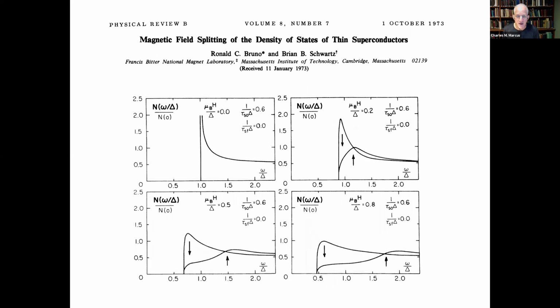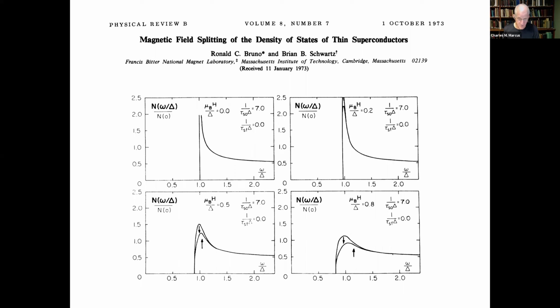But it's interesting to look at what happens, at least in these theoretical plots, when you turn on, in this case, spin orbit coupling. Here are the two bands, and you see that their densities of states don't go to unity, they change, but they go together now because there's enough spin mixing between the two. And the same thing is true here, with very strong spin orbit coupling, and you see almost nothing happens. There are almost no two bands. This is now for the case of very strong spin orbit coupling.